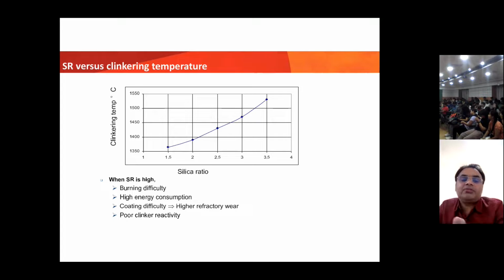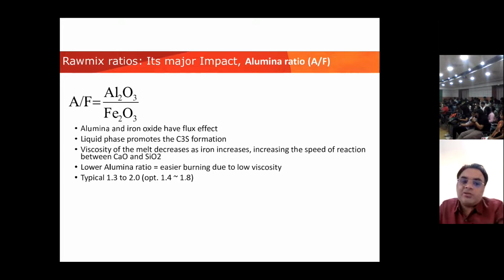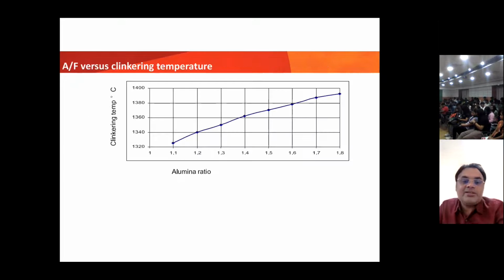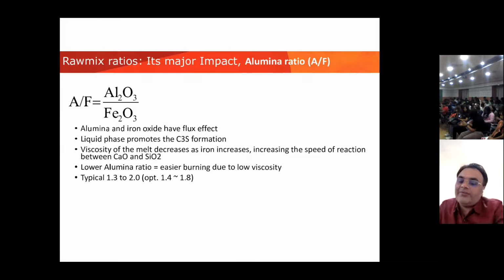Similarly, so what will happen? I told you that if it is high, the burnability will be difficult, with high energy consumption and poor clinker quality. So you have to keep it in that range, right? Similarly, it is for the alumina modulus, or A upon F, range. It contains the flux effect, because inside the kiln the raw material is burned. So liquid is very important in that one to make the nodules.